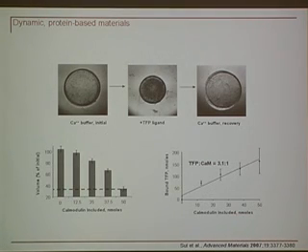So the next question, once incorporated into a hydrogel, do these molecules actually undergo the conformational shift? Do the materials undergo a volume shift? And here again, you're looking at top views of cylindrical hydrogels, initially in calcium-containing buffer, then in the presence of trifluoperazine ligand that induces the Calmodulin shift. And you see this pronounced collapse in the volume of these materials. And then back in calcium buffer for recovery.